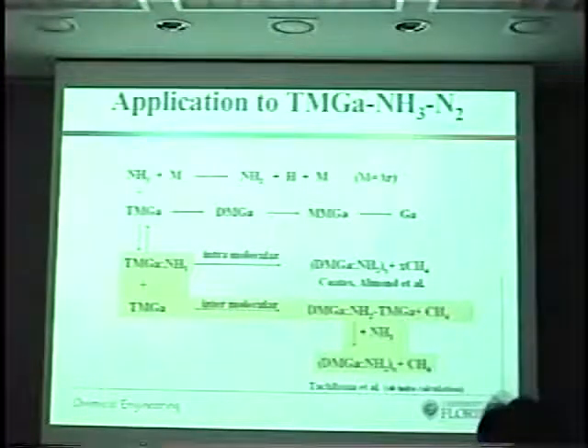But that's not the whole story, because ammonia decomposes very slowly. It requires a high temperature. Whereas trimethyl gallium begins to thermally decompose around 200 degrees C. But yet we're able to grow. In fact, that was the breakthrough that allowed, I believe, the first blue LED to be made: a reactor design change that allowed trimethyl gallium and ammonia to be delivered in a way that could react at the surface and produce gallium nitride at 1,000 degrees centigrade.